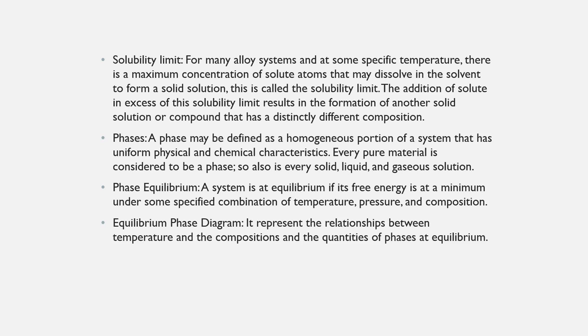Phase equilibrium: equilibrium is best described in terms of a thermodynamic quantity called free energy. Free energy is a function of the internal energy of a system and also the randomness or disorder of the atoms or molecules. A system is at equilibrium if its free energy is at a minimum under some specified combination of temperature, pressure, and composition. In a macroscopic sense, this means the characteristics of the system do not change with time.